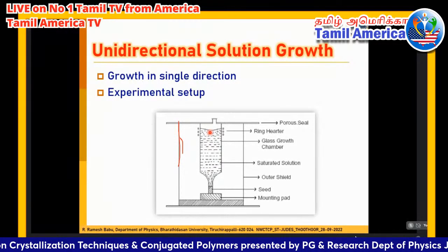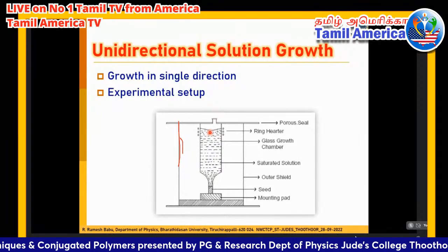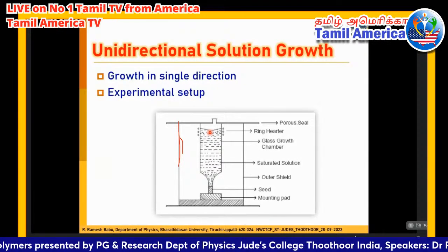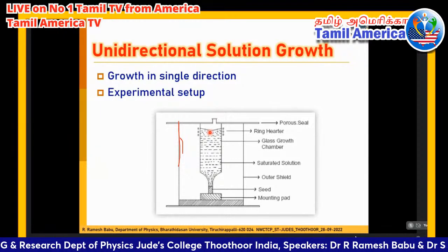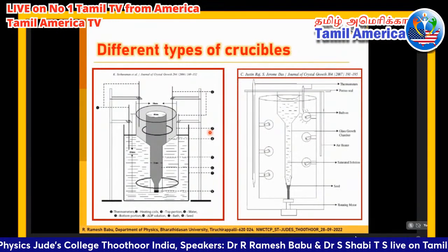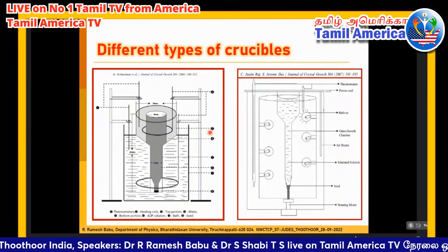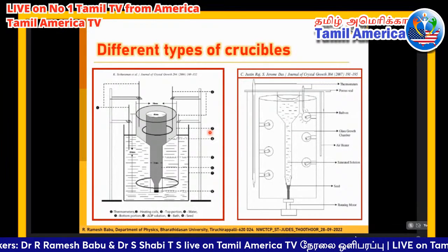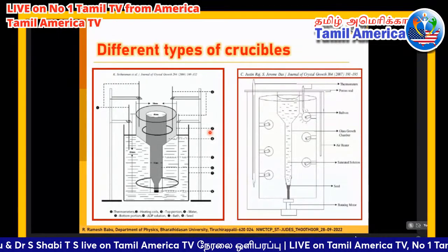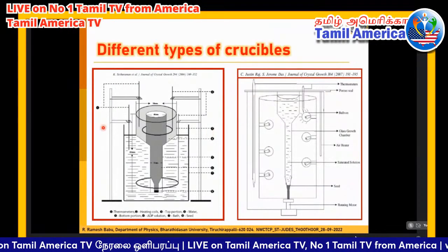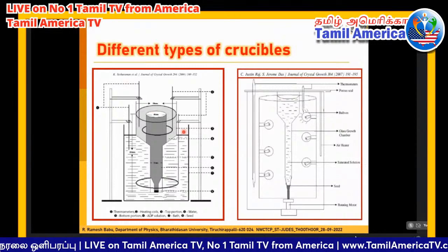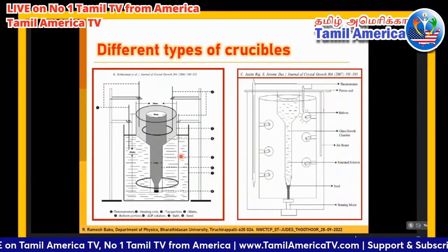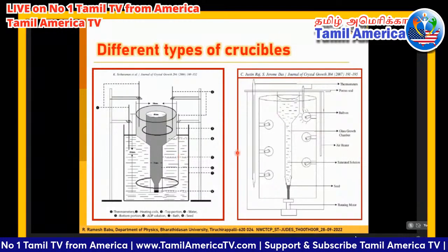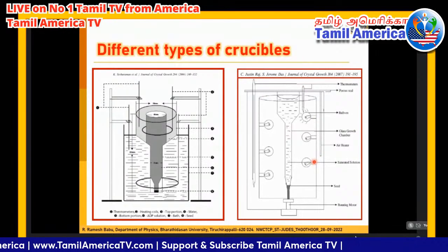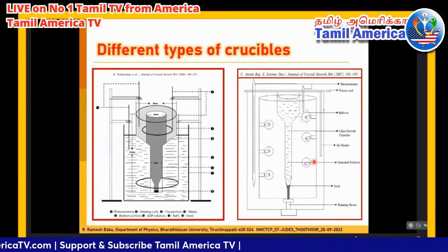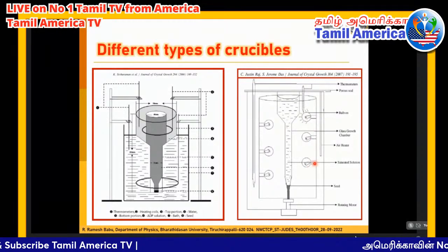So we can grow a bulk single crystal, as well as convert 100% of the solute into crystals in this technique. Following this technique, there are n number of investigators involved in the growth of bulk single crystals by this unidirectional technique. Myself, Dr. Sethuraman et al., we used this type of vessels to grow ADP single crystals, and then Justin Raj et al., in order to provide the heat to the vessel, used bulbs. So instead of using heaters, they use bulbs.